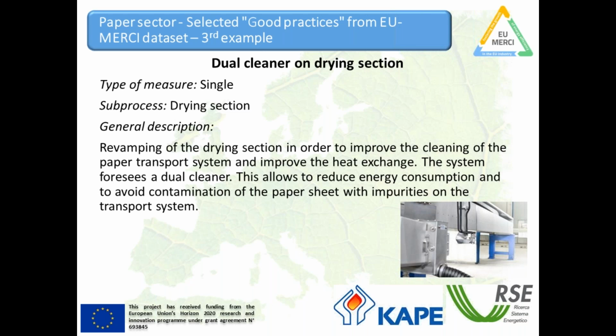The third example is something that stays in the middle. It's again a single measure on the drying section, and it's a revamping on the drying section that is not invasive, but it's easier than other improvements to be put in place. And it's very easy also to understand. They just improve the cleaning of the paper transport system in order to improve the heat exchange between the paper and the heat exchangers, and the steam mainly, and so reducing the consumption of natural gas that needs to be burnt to obtain the steam used for drying.